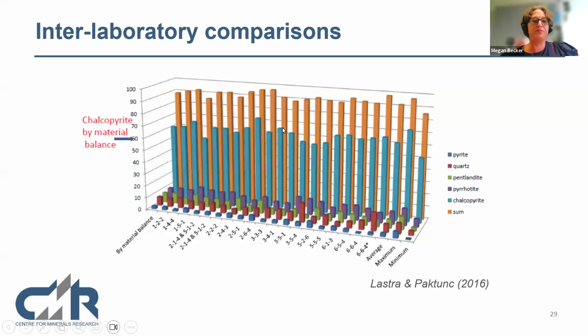So what happened with the results? The material balance of chalcopyrite was about there, and here you see the variability came out. Essentially, every group was given the same sample or a representative sample of the same material, but the chalcopyrite grades could vary between up to 80% or 60%, so there was obviously close to a 20% spread, 10% above and 10% below what the groups came out with. Now, if any group had been using back calculated copper grades, you would have spotted if this was your measurement up here, or that was your measurement down there, that you were either overestimating or underestimating copper.